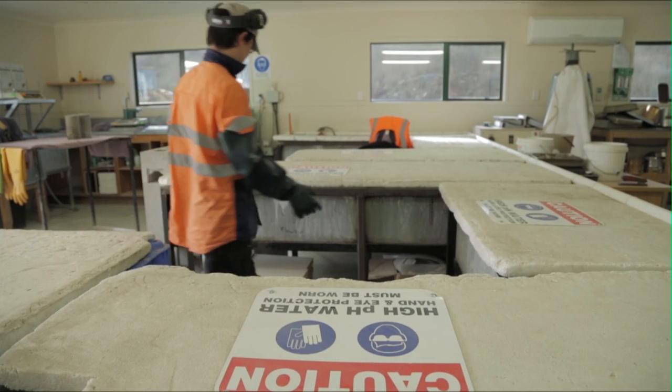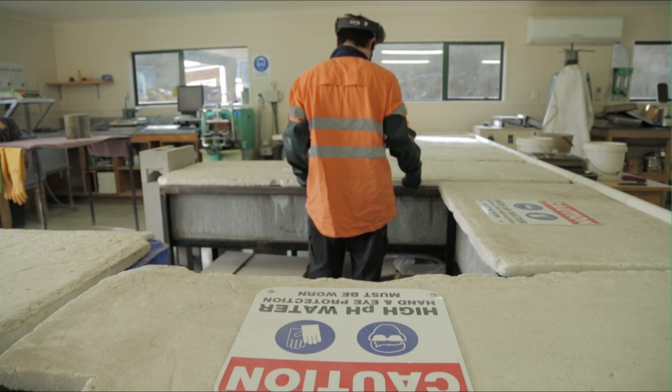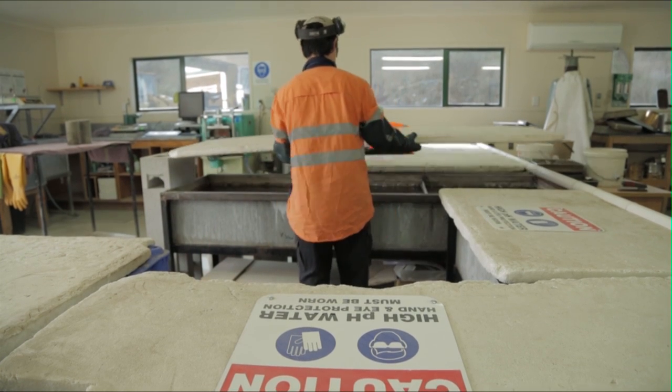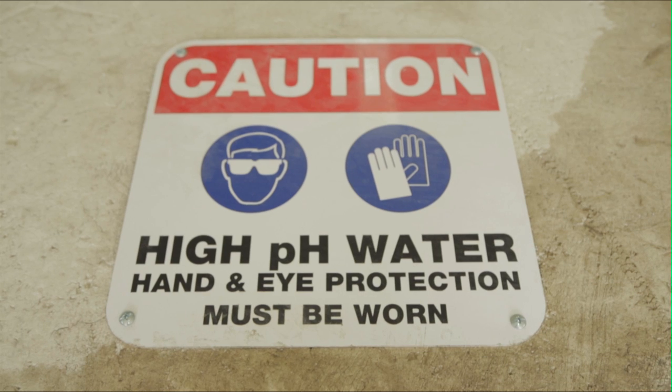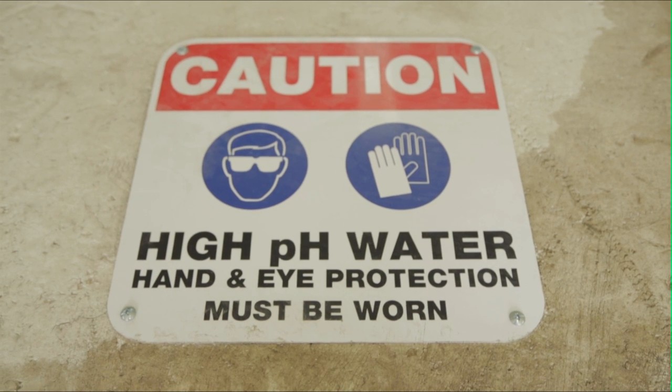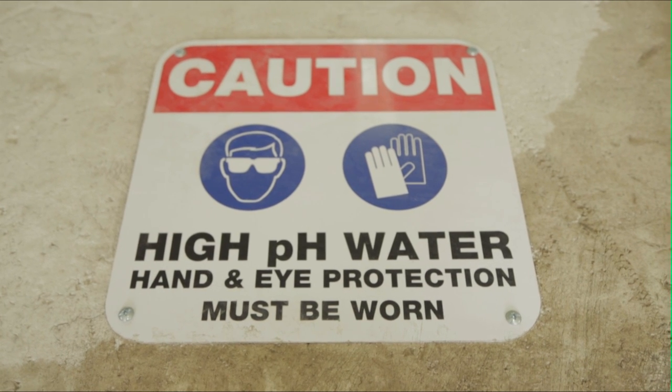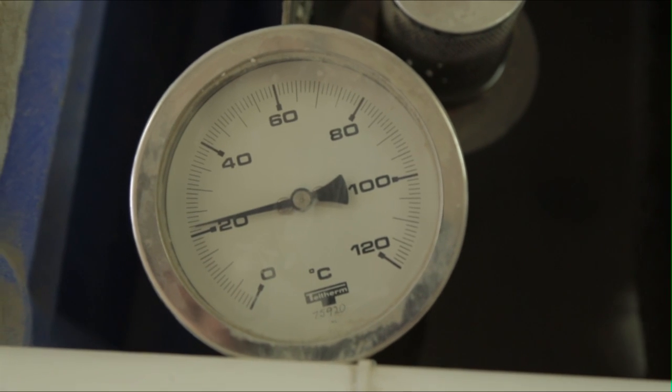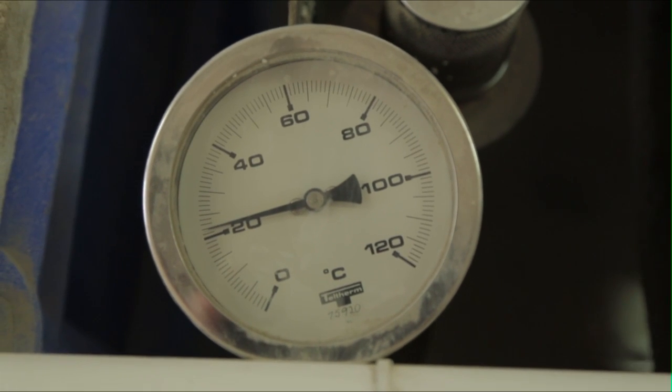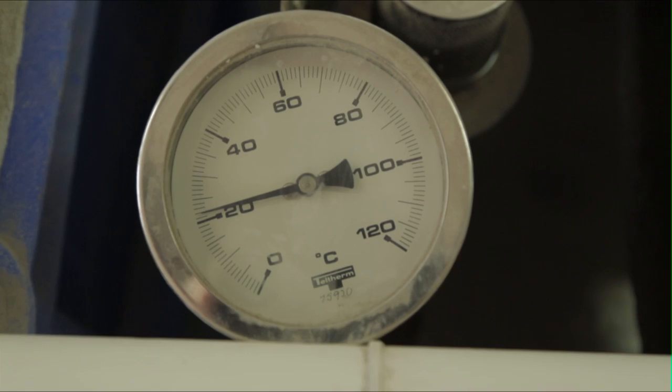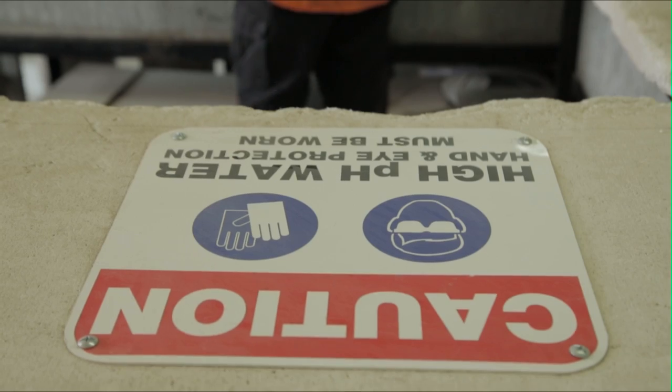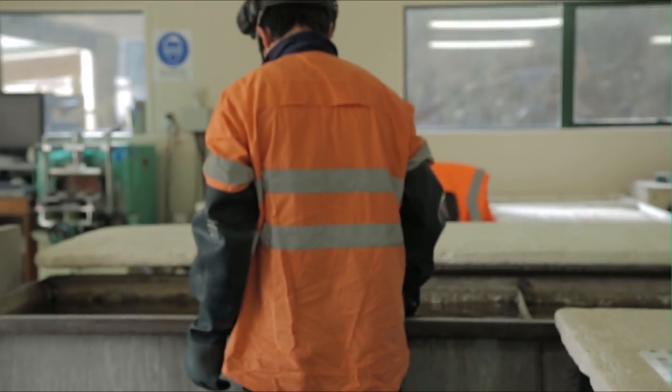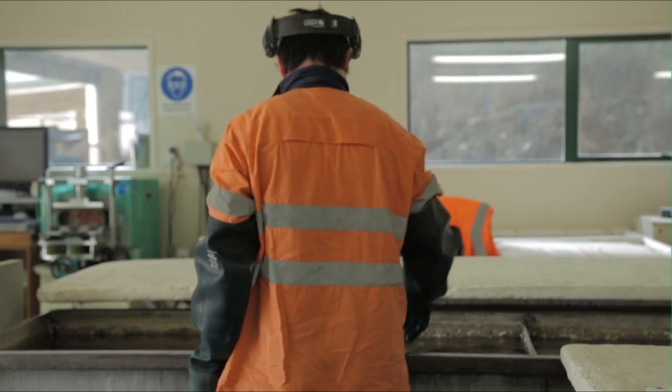Retrieve the cylinder from storage. Note the concrete containing water baths are extremely alkaline and hand and eye protection should be used. Also note the standard states that the cylinders should be stored in the lab at a temperature of 21 degrees Celsius plus or minus 2 degrees Celsius.